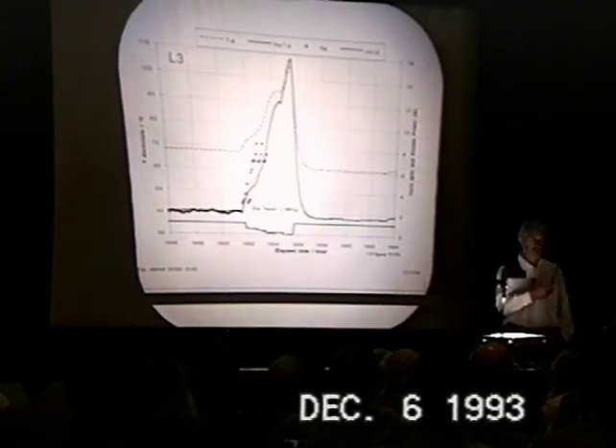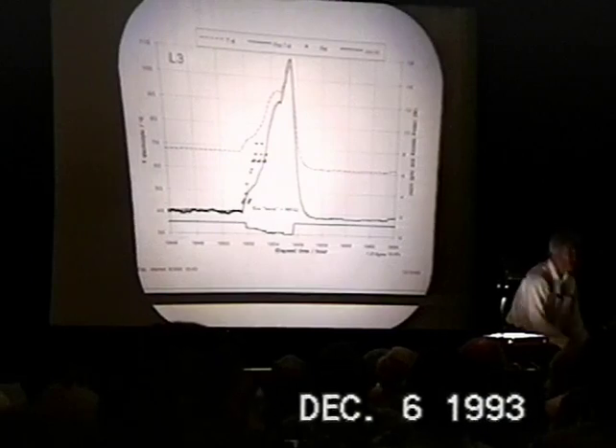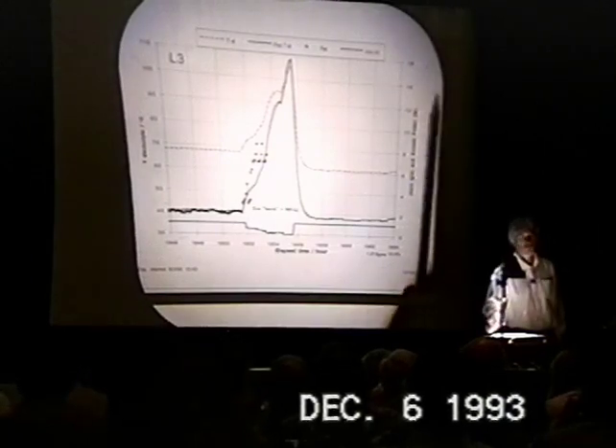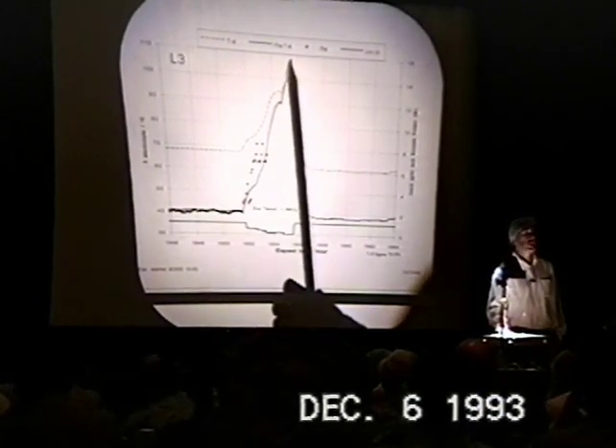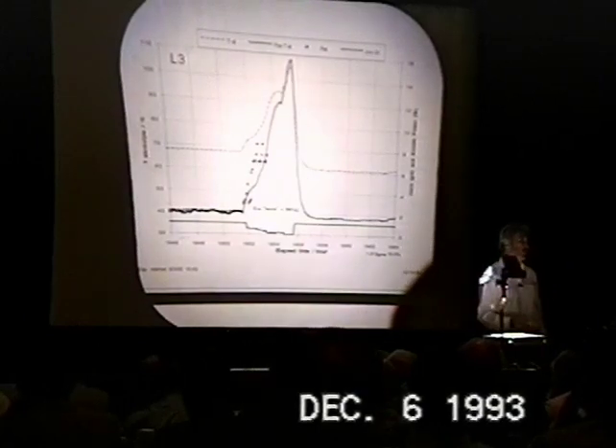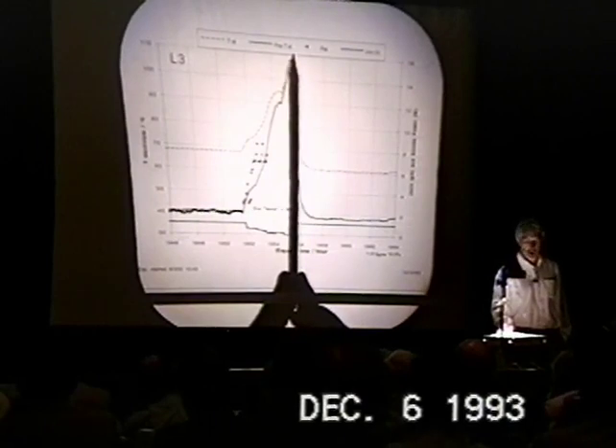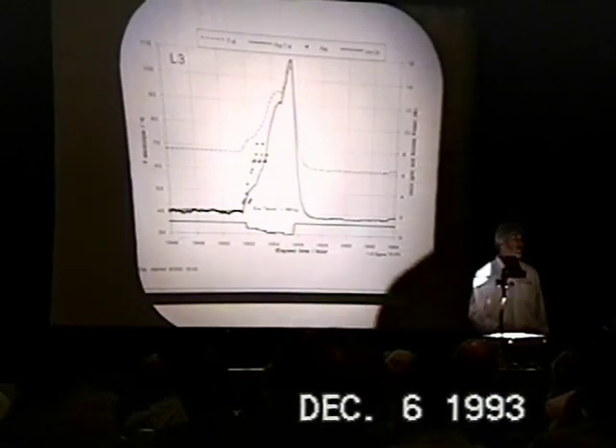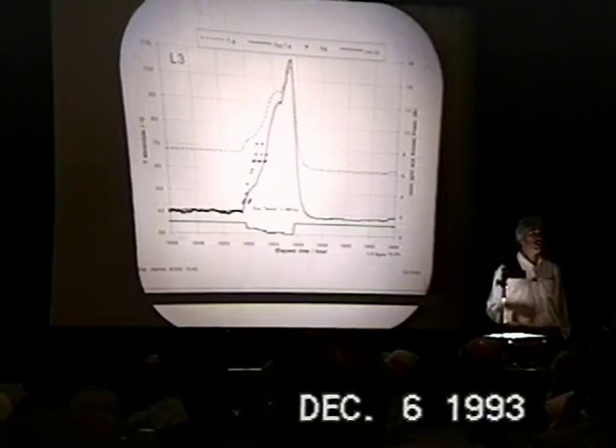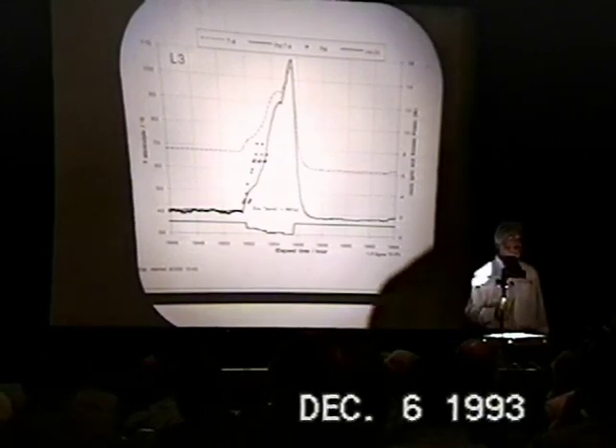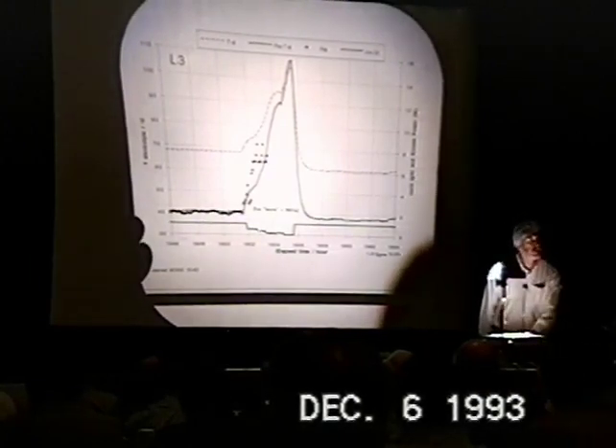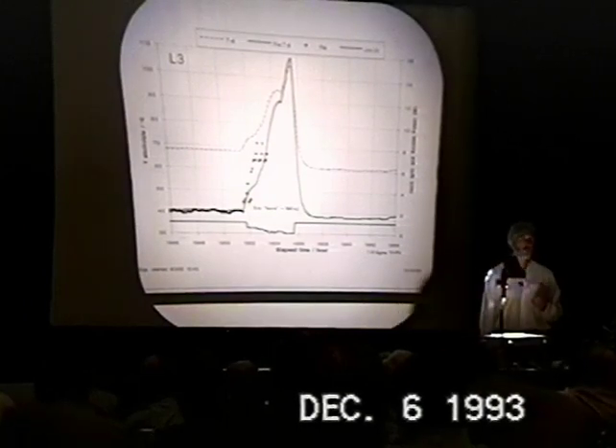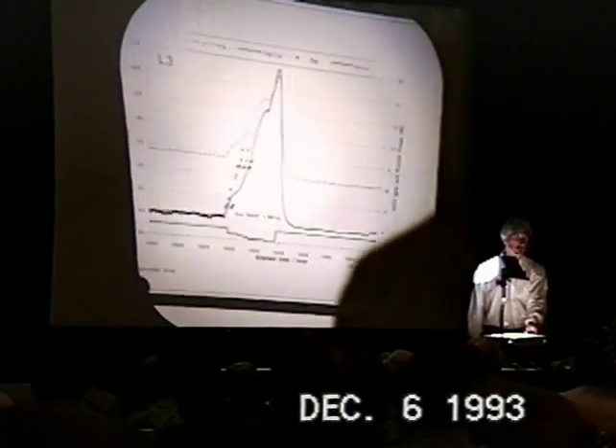Now in Fleischmann-Pons terms, this is not a spectacular amount. There's about a third of a cc of palladium there, so it's less. Even at 16 watts of excess power, we've got about 100 watts excess per cc of palladium. It's not a prodigious amount. And this is 16 watts in 60 watts, so as a percentage it's not large, but it's nevertheless a fairly large effect that seems to have been stimulated by a rapid increase of the electrolyte temperature and therefore the cathode temperature, much in the way that Martin described one ought to do one's experiments. It's a shame that we only found out about it by accident.